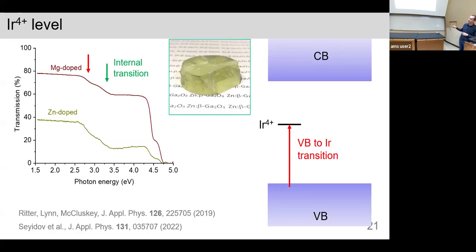By the way, zinc dopes showed qualitatively the same spectrum. Zinc is another acceptor. So we knew that this absorption was not due to the magnesium because of that. So it has this kind of interesting yellow color. If it doesn't have the yellowish color, the crystal grower immediately knows that something went wrong.